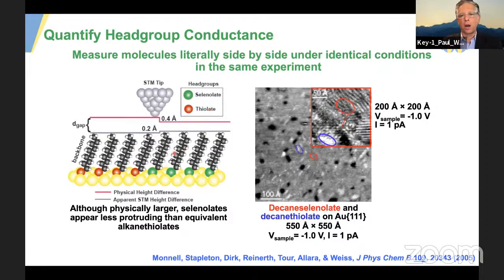And so we set out to put the molecules in the same structure. Selenium's lower in the periodic table. You can tell I teach first-year undergraduate chemistry. So the selenium's a little bit larger. It actually turns out it's a little more promiscuous on the surface, but we can force it into the same structure. And this schematic is drawn correctly in that the tip had to go closer to the selenolate molecules of the same backbone chain length.